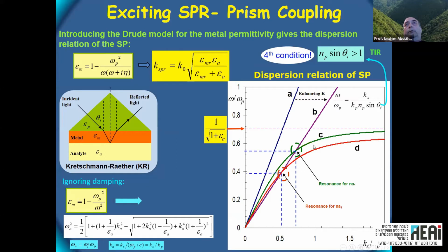In order to be able to excite it, we need to change this angle here, the slope of the dispersion curve. And for that, we use the coupling medium. That means omega versus k. It means we need to have here a factor which will give us a smaller angle.